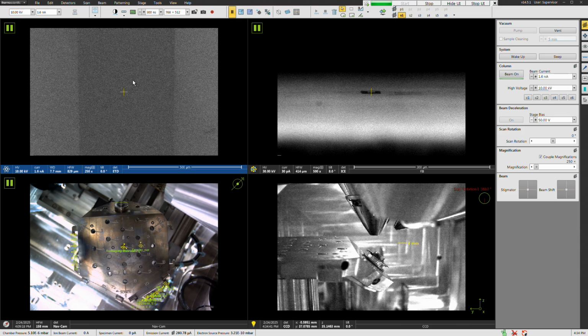All right, let me switch back to here. Okay, so now beam voltages for doing EBSD. 10 kilovolts is about the lowest you can do this effectively, at least on this camera, 30 being the highest. Generally speaking, the coarser the microstructure, the higher the voltage you can use. I think EDAX recommends 20 as a default if you're not really sure one way or the other. The camera responds better as the voltage is increased, so there's that to consider. Generally speaking, though, I find the response when you switch from 20 to 30 is kind of negligible in terms of the improvement that you get. The response improvement tends to be more pronounced when you go from like 10 to 20.